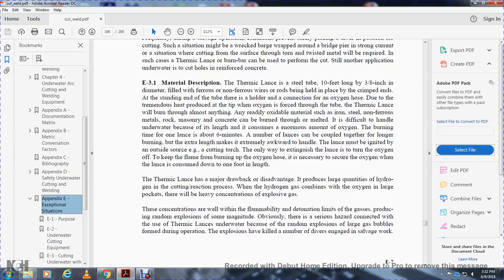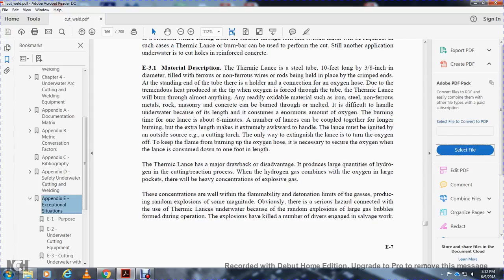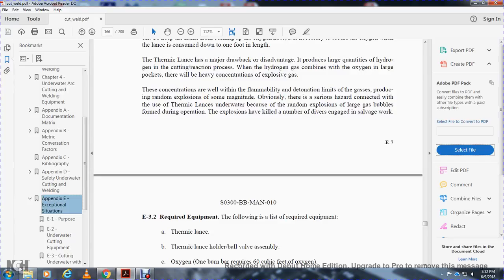The thermic lance has a major disadvantage: it produces large quantities of hydrogen in the cutting reaction. The hydrogen gas combines with the oxygen in large pockets. There will be concentrated explosive gases. The concentrations are well within the flammability and detonation limits of the gases, and periodic, random explosions of some magnitude occur. Obviously, there are some hazards connected with the use of the thermic lance underwater because of the random explosions with large gas bubbles formed during operation. The explosions have killed a number of divers engaged in salvage work.